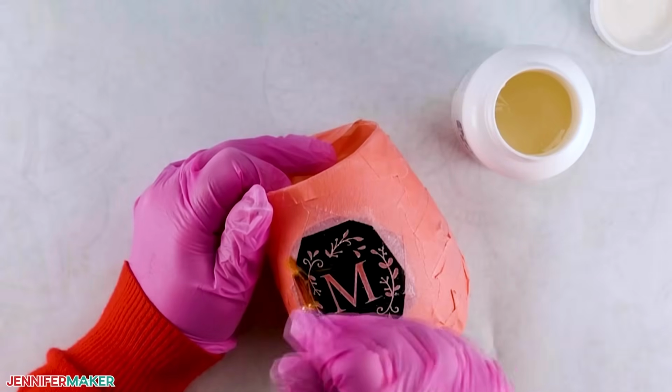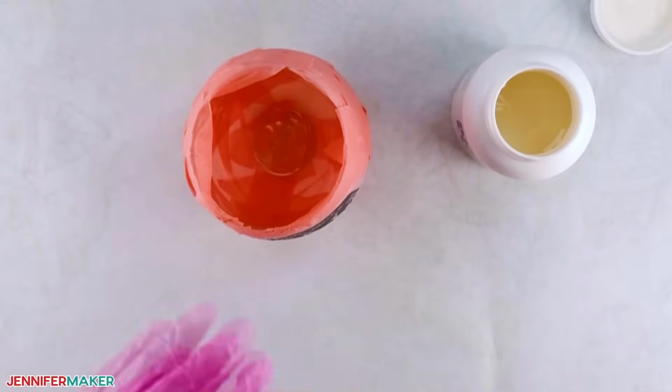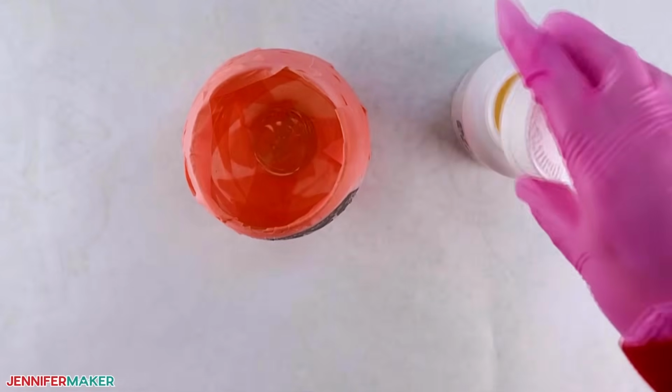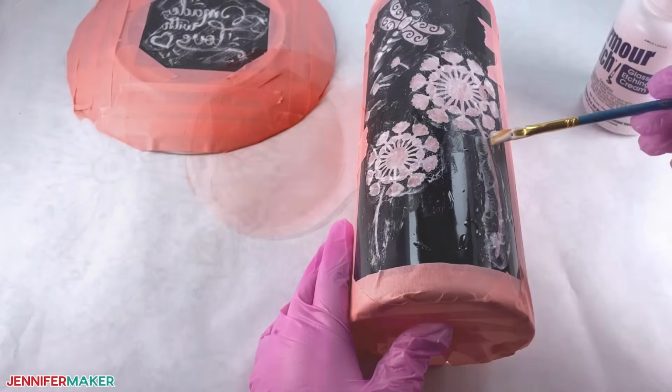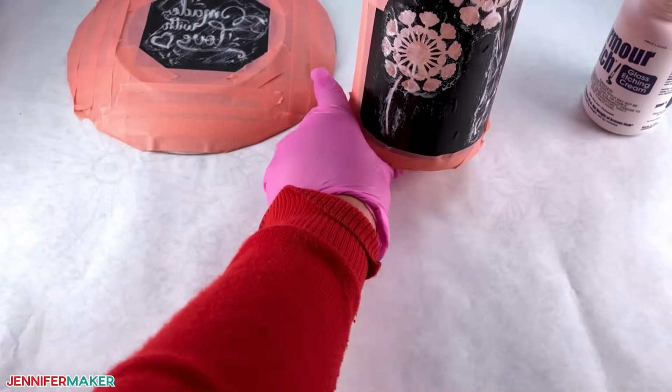After the 3 minutes are up, apply more cream in areas where it looks thinned out, and then let it sit for another 5 to 10 minutes. Letting the etching cream sit on the glass for longer creates a more uniform and deeper etch. This works especially well in larger areas, such as the vase design.